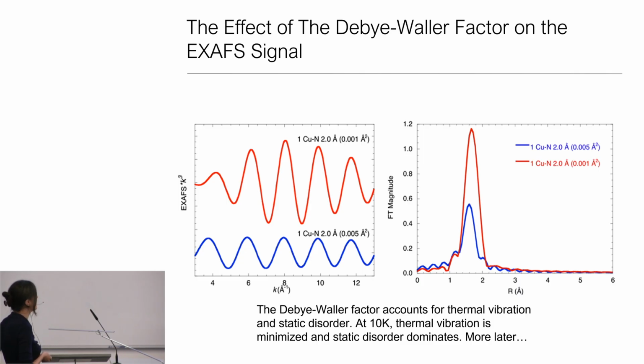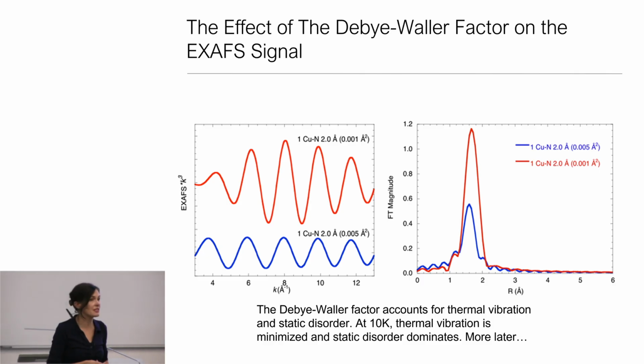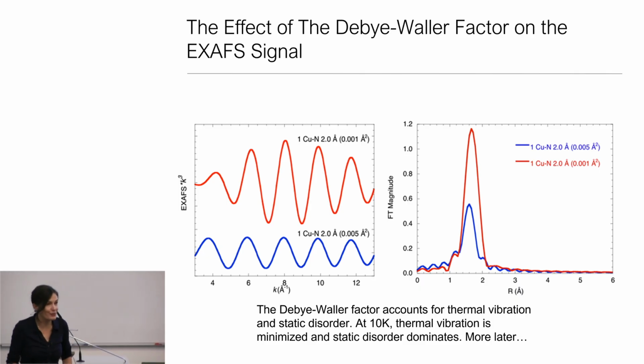The last one I want to point out, and it's an important one, is the effect of the Debye-Waller factor. This is the disorder term. It accounts for thermal vibrations, but it also accounts for static disorder. Most of the time in our group, we try to do EXAFS measurements at low temperature to minimize the thermal contributions. That'll generally give you nicer data. But if you're doing an in situ experiment, you can't do it at 10 Kelvin, so you have to model the thermal and the static parameters into your EXAFS. I'm going to talk more about static disorder later, so I'll leave that out for now. But basically, the bigger the number of the Debye-Waller factor, the greater the static disorder. So if I have more disorder, the intrinsic intensity goes down.